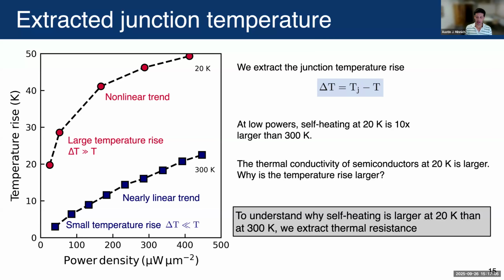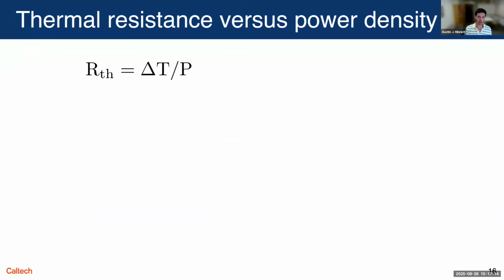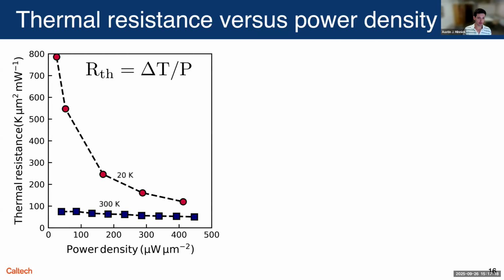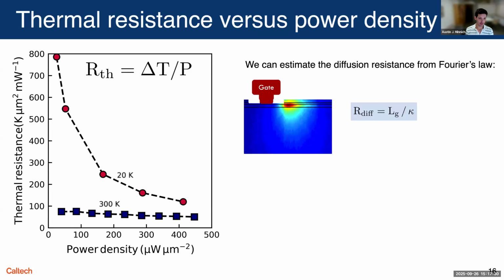So to understand how we can reconcile those two viewpoints, we can do a bit more analysis. We can next extract the thermal resistance, which is just the temperature rise divided by the power. That's plotted again versus power density. And you can see again 300 Kelvin and 20 Kelvin results. And you again find that the 300 Kelvin is basically independent of power, but the 20 Kelvin resistance has to change with bias to explain the data.